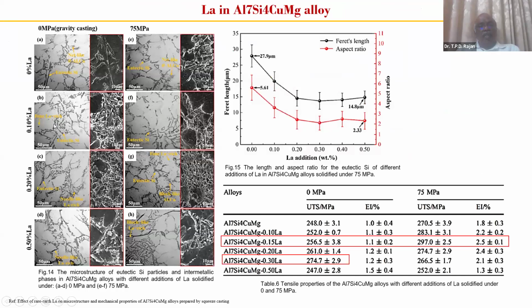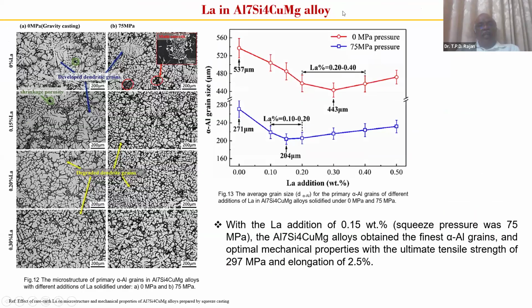Again, this is also how the addition of lanthanum in aluminum alloys, especially aluminum-copper alloys, refines the grain structure. These are all the alpha phase, which is getting refined by the addition of lanthanum into the aluminum alloys, especially in a very fine quantity. This shows the reduction in the aluminum grain size with a very minor percentage. At around 0.5 percent, it shows almost 443 micrometers.